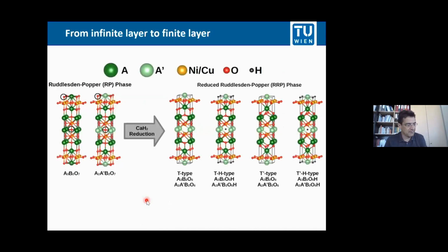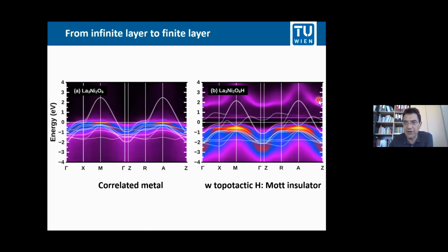Okay, just as my time is running out, we also have looked at layered nickelate compounds. So you can start with this Ruddlesden-Popper phase and do the same calcium hydride reduction to get bilayer structures here. This T' type is more stable. You can also have topotactic hydrogen here in black in this structure. It's a very similar story as for the infinite-layer compound.